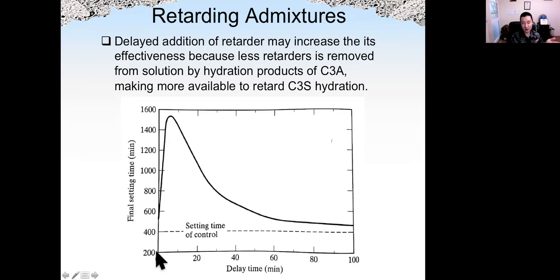Why would only a 10 minute delay increase setting time by that much? The reason is shown here. Initially we mix water with cement, and there is a lot going on from hydration of C3A, because C3A reacts super fast. So we do not add retarder at the beginning; we let the C3A react. But after 10 minutes, we add retarder, so that will make retarder more available to work on C3S hydration. So that's why with only a 10 minute delay, we have much more effectiveness on the final setting time.